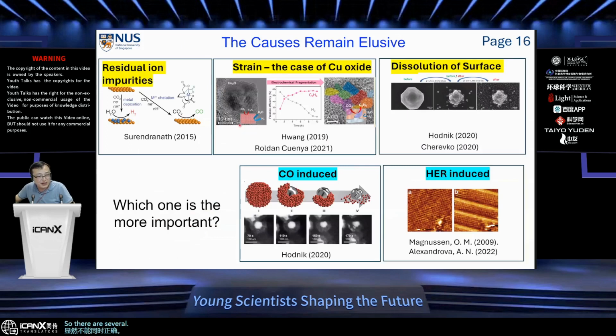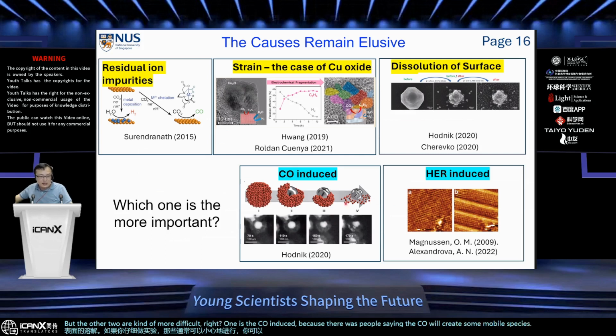So there are several hypotheses about why this happens. There are several that can be easily screened out, right? Including the impurities in the electrolyte, the strain, the dissolution of the surface. If you do the experiment carefully, you can exclude them. But the other two are kind of more difficult, right? One is CO-induced, because there were people saying the CO will create some mobile species of the copper, and cause this sort of disintegration of the particle. The other is the HER-induced, the hydrogen evolution reaction. The hydrogen is responsible for it, and both are involved in the CO2 reduction reaction. So, kind of difficult to either control them or get rid of them.